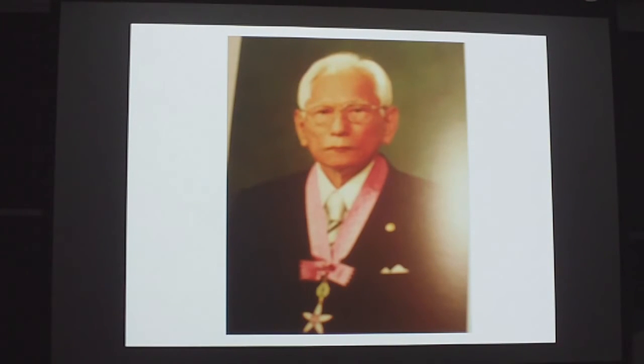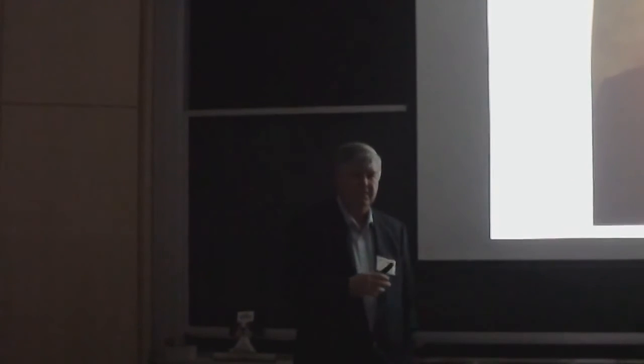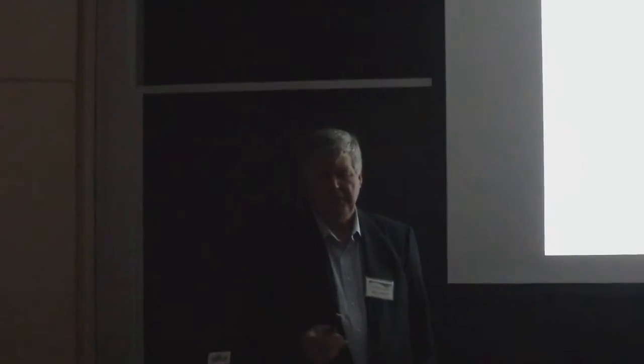But right after his presentation in 2008, Akito Takahashi got up and made the same presentation, and he found that they didn't see any excess heat. But his powders were 20 to 100 nanometers. So I communicated with him over January of 2009 saying, if you get to 5 to 10, you'll see the result. And by March, they had done that, and they saw the improvements.